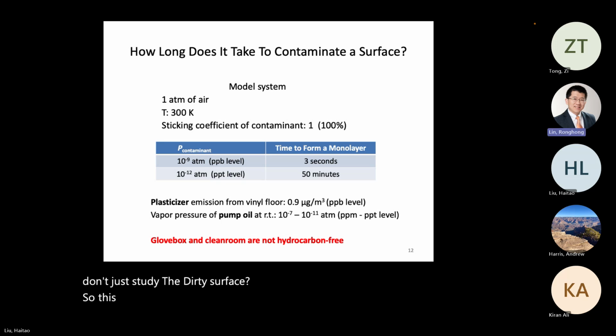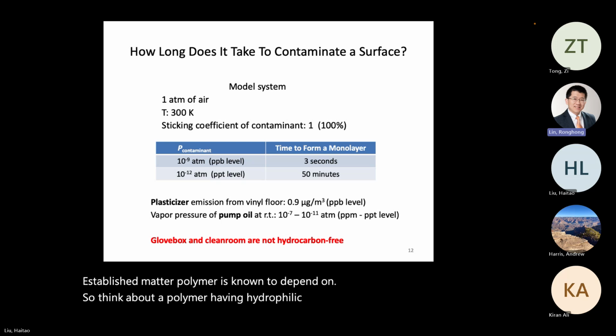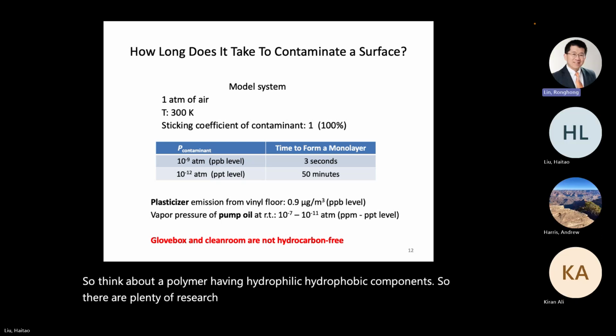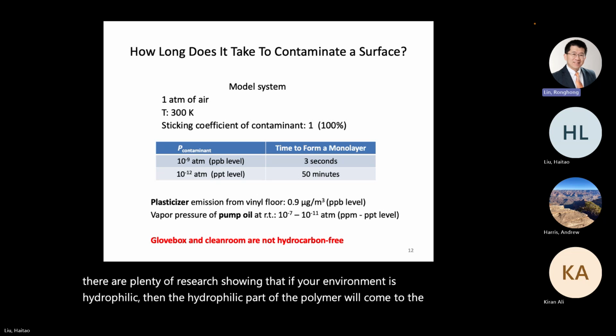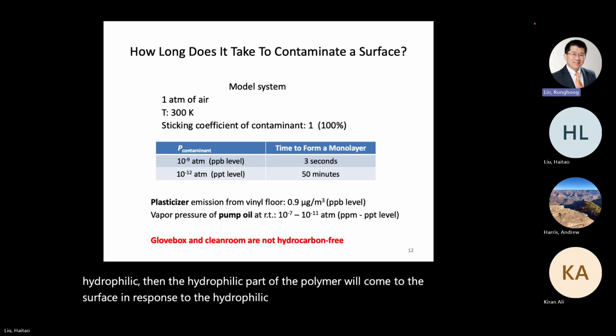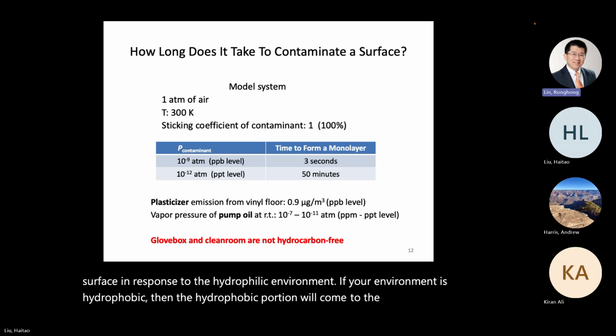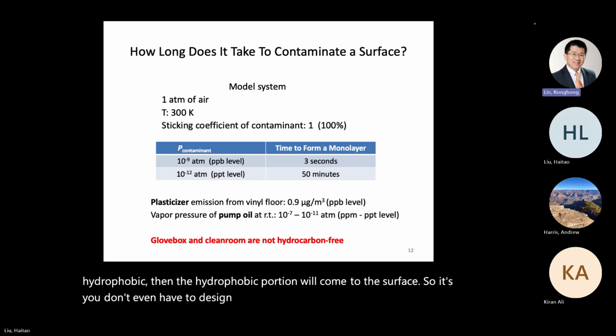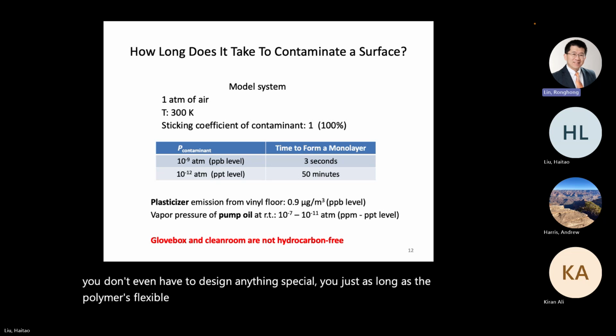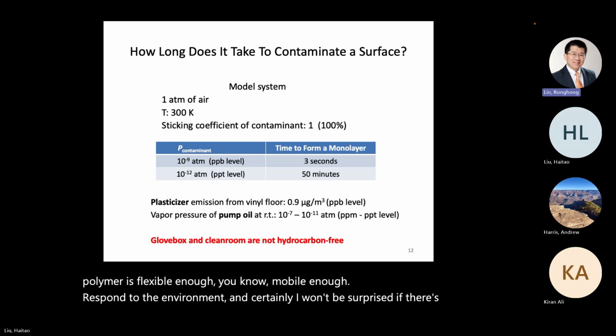So this will also impact polymers, because contact angle is a well-established method. Contact angle on a polymer is known to depend on the environment. So think about a polymer having hydrophilic and hydrophobic components. There is plenty of research showing that if your environment is hydrophilic, then the hydrophilic part of the polymer will come to the surface in response to the hydrophilic environment. If your environment is hydrophobic, then the hydrophobic portion will come to the surface. So you don't even have to design anything special. As long as the polymer is flexible enough, mobile enough, it will respond to the environment. And certainly I won't be surprised if there's absorption happening on this polymer as well.